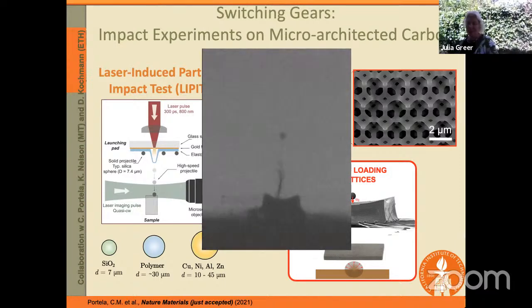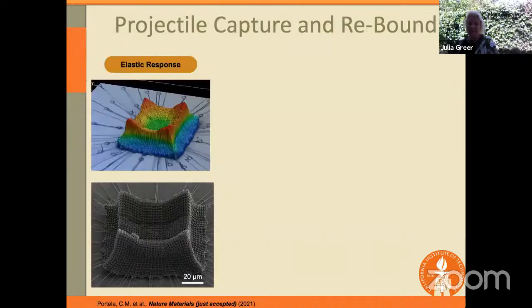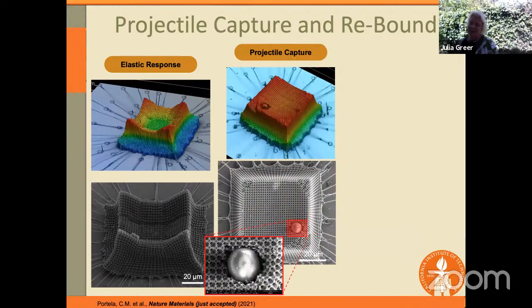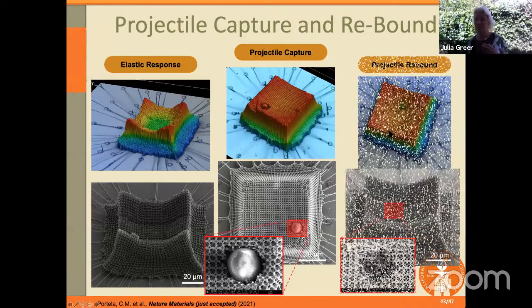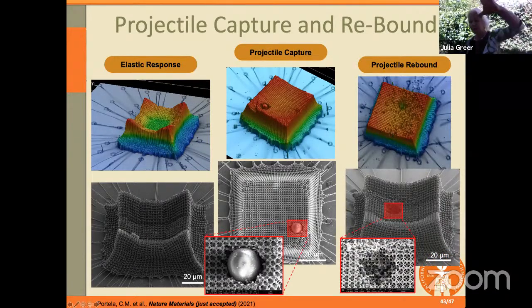So here's a movie that shows one of these projectiles as it hits. It's effectively a small bullet, right? As it hits this material, what we are discovering is that there are 3 different regimes. Sometimes the response is entirely elastic, so it just rebounds. The second type of response is projectile capture. And then the third type of response is the projectile rebound, where the projectile hits the nanolattice, but it's not elastic. There's an impression left, and then it rebounds.